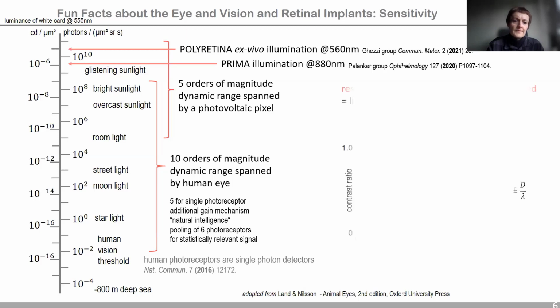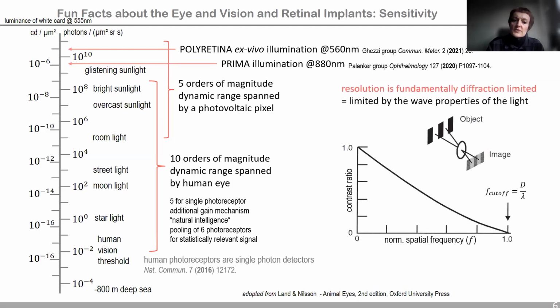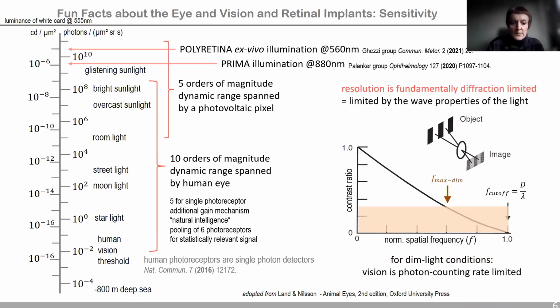glistening sunlight. However, the resolution of human vision depends on seeing contrast between 2 objects rather than seeing absolute intensity. If the contrast ratio goes down to 0, then these objects can no longer be resolved as 2 different objects. In the end, the contrast transfer function is limited by diffraction, and that is again the wave nature of light. Under dim light conditions, the contrast ratio threshold goes up. This is because of an additional gain mechanism that requires several photoreceptors to respond independently to come over the stimulation threshold.